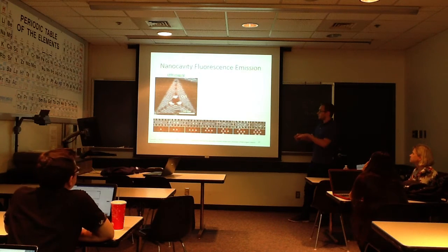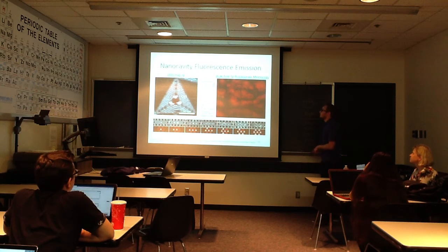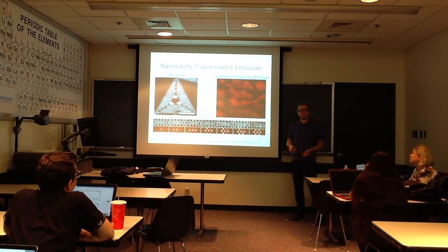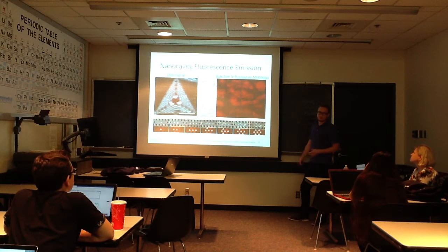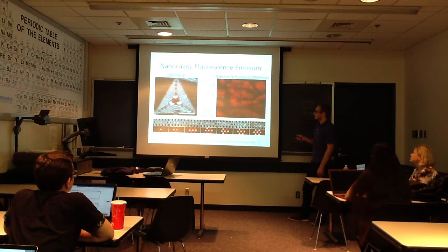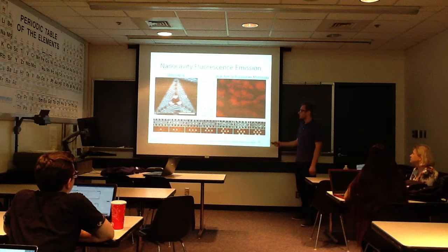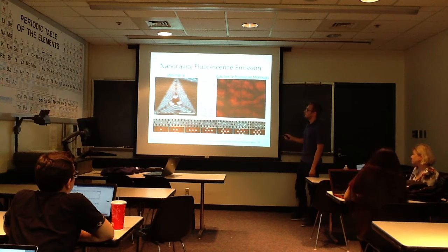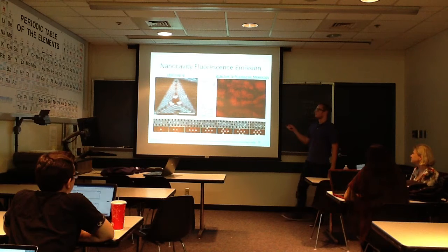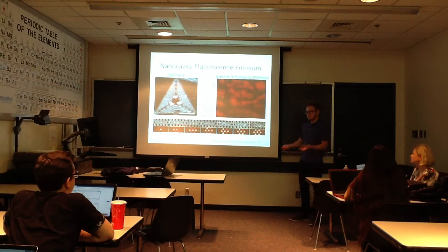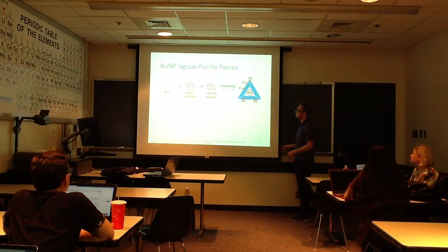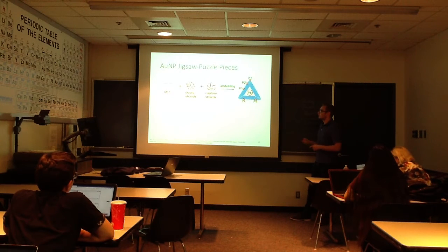And so when you put it all together, say you have a sheet that you want to manually design, you can generate different kinds of images from those intensities and make actual images at the nanoscale level. So this is Van Gogh's Starry Night, imaged using these fluorescent DNA origami constructions. We were able to see that the intensity they wanted to intentionally modify, they were able to do with quite a degree of accuracy, based on the number of sites they wanted, and I think it was 65,000 different individual cavities in which they were able to place their desired amounts of intensity in terms of DNA origami.